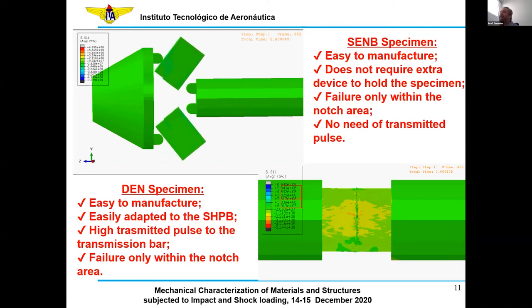We also must have a fairly high transmitted pulse in the bar in order to measure the strain rate by using the unidimensional stress wave propagation theory. And also we must have a reasonable amount of reflected pulse in order to compose the strain within the specimen, right? With the strain within the specimen, and also with the forces at the bar ends, we can actually compute the stress and have the stress-strain plots for different strain rates, and also quantify with these quantities the intralaminar fracture toughness at different strain rates.